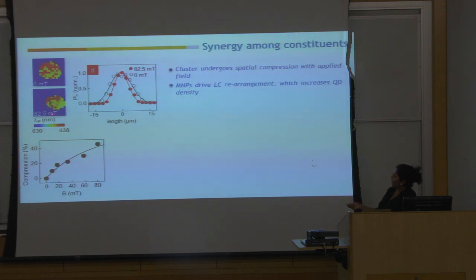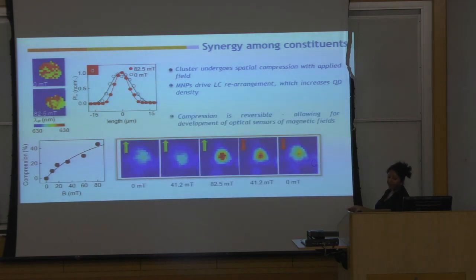We also find that with the application of field, the clusters get squished. So we are plotting the cross-section of the clusters, the spatial cross-section. With the application of field, they are always narrower. So somehow, when we apply the field, the liquid crystal is reorienting in a way that is squishing the clusters closer. We can actually calculate the compression factor of the clusters as a function of field through this imaging. And also, this effect is reversible. When we turn the field off, the whole arrangement relaxes, and this brightening goes away. It's a little bit hysteretic. After all, it's a spatial arrangement on this scale. It's not going to be exact. When we remove the field, the effect goes away.